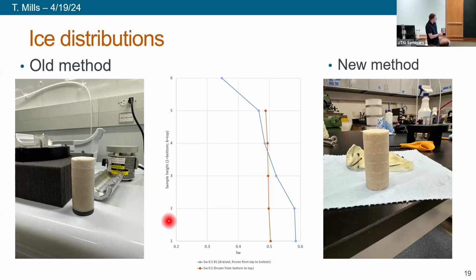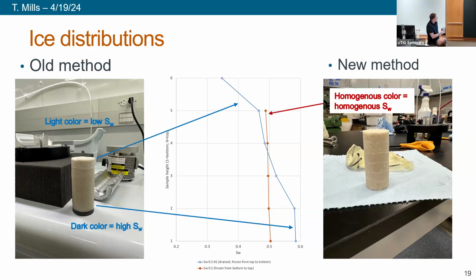And so this plot here in the middle is showing our sample height from the bottom to the top and the saturation of the sample as a function of that height. So our sample over here on the left, that's our old method, you can notice the top of it has a really light color at the top and a dark color down at the bottom. So this dark color corresponds to a really high saturation of water, and our light color corresponds to a really low saturation of water. However, our new method, we've got this nice homogeneous sample, and here we have a nice homogeneous distribution of ice. And so we were finally really satisfied with being able to make a synthetic sample.